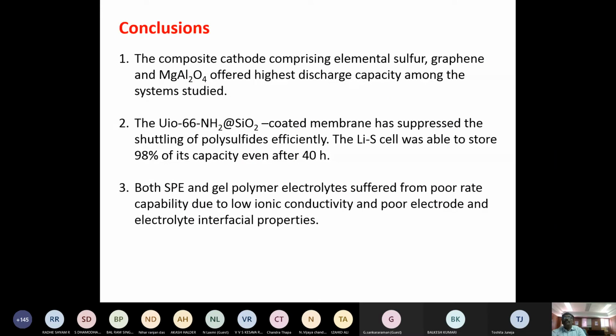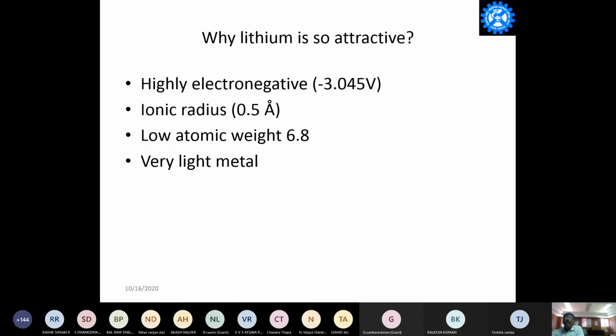Among the systems coated, the UiO-66-NH2 SiO2 coated membrane has suppressed the shuttling of the polysulfides efficiently, and the lithium sulfur cell was able to store 98% of its capacity even after 40 hours. And when we applied solid polymer and gel electrolytes, it suffered from poor rate capability because of the low ionic conductivity of the membrane.